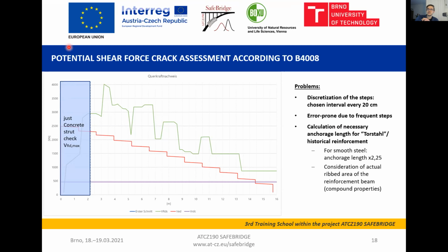So in green here is the result. In red we have the shear force we have to design for, that was derived from the analysis, and in green we have our calculated line, and so you can see the shear force check is okay. The shear force only has to be checked after the critical crack length that is calculated.